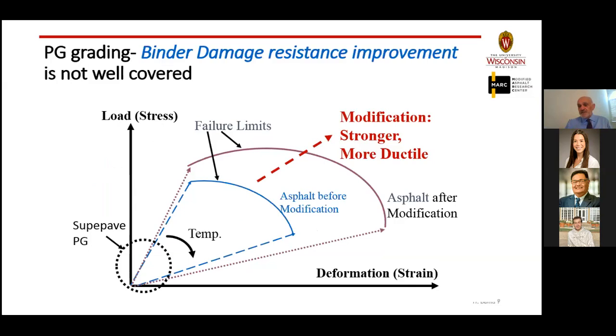And what we found is most of these really successful modification techniques will actually change the location of the failure envelope. Again, I'm going back to really elastic behavior with very simple stress and strain, and forgetting about the time domain, because really the time domain is just an additional complexity. But we see a very significant increase in the failure limits when you put modification into asphalt.